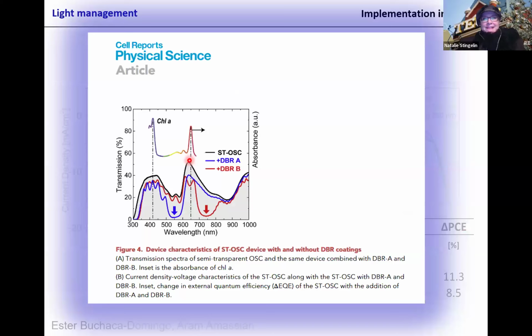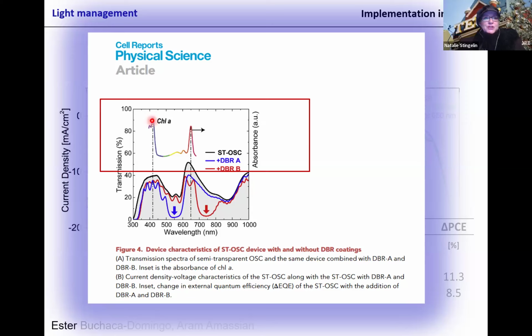Why is that important? A single device, it helps with efficiency, but if you really want to integrate those devices somewhere, for instance, in a greenhouse, you can play with that. In a greenhouse, you have to make sure that you have relatively high transmission. Here, the black, that's again the solar cell, where the chlorophyll absorbs. So here on the top, you see the absorbance of chlorophyll. It's around 400 and 650. Why chlorophyll? This is one of the key ingredients, the key chromophores in plants that absorb light.